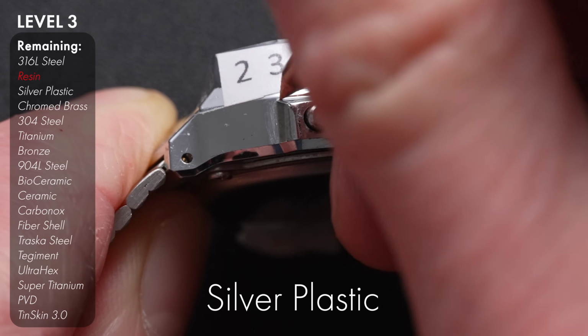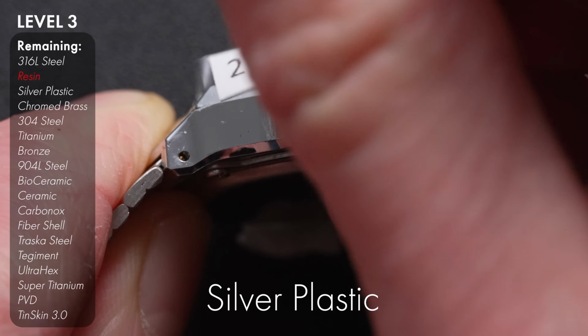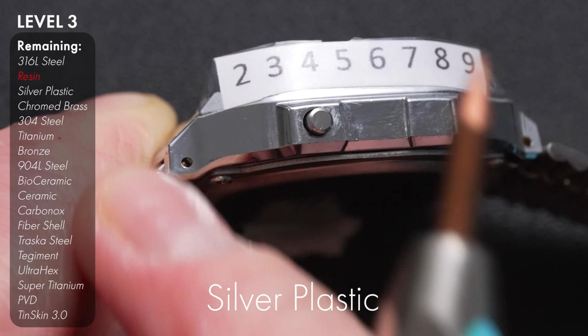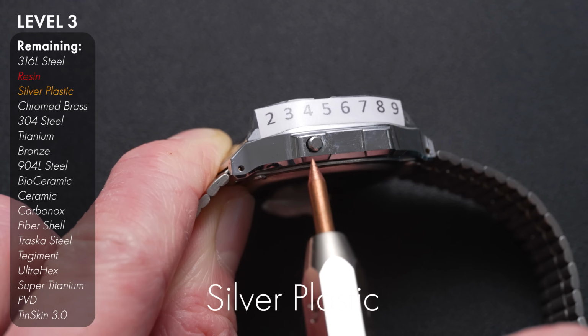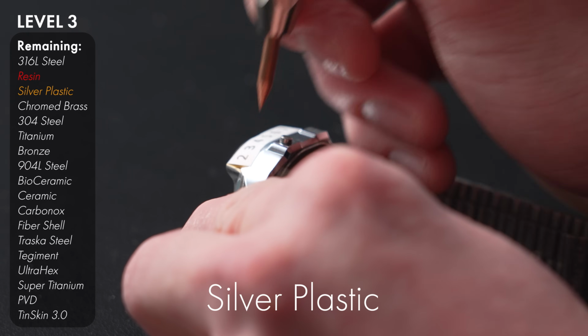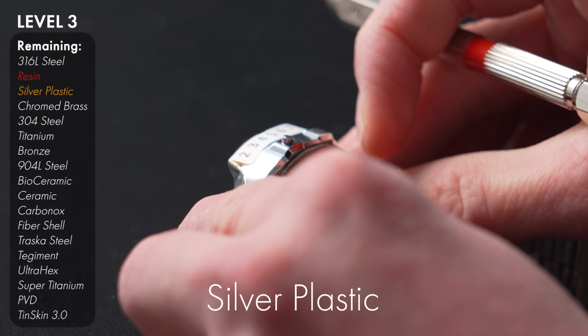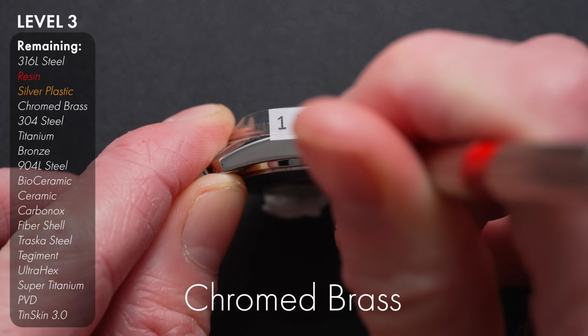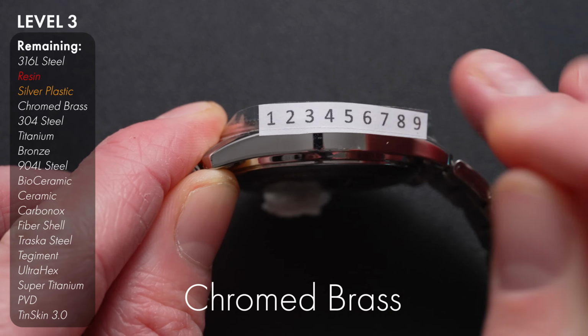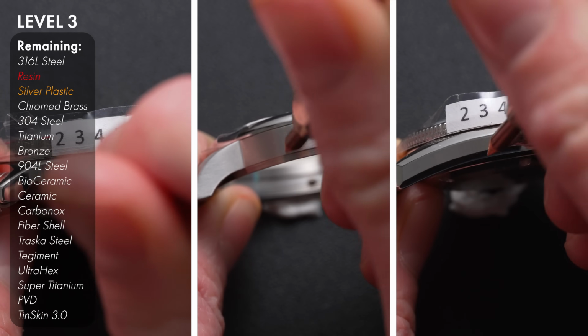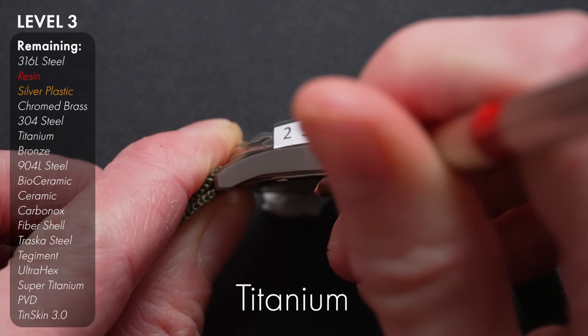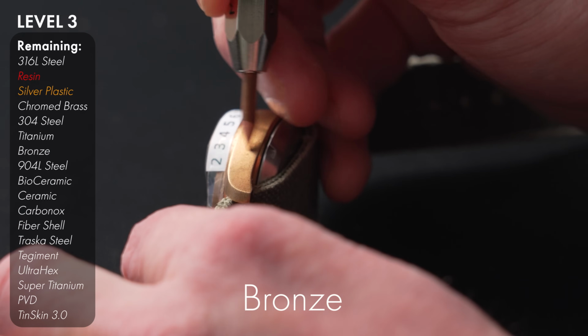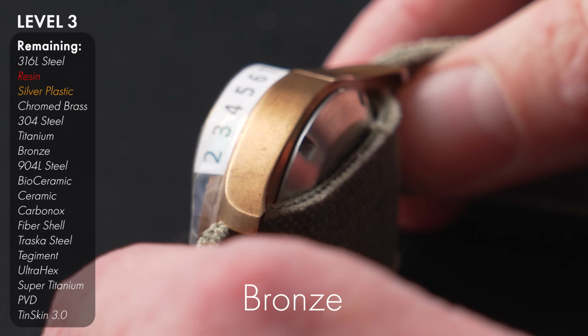I think it has scratched, but the scratches are far less deep and prominent than those on the black watch. So it's definitely a little bit better, these plated watches. The chromed brass case, which I had low expectations for, passed with no issues, as did all of the steel watches and the untreated titanium. Despite being a fairly soft material, bronze also had no trouble here.